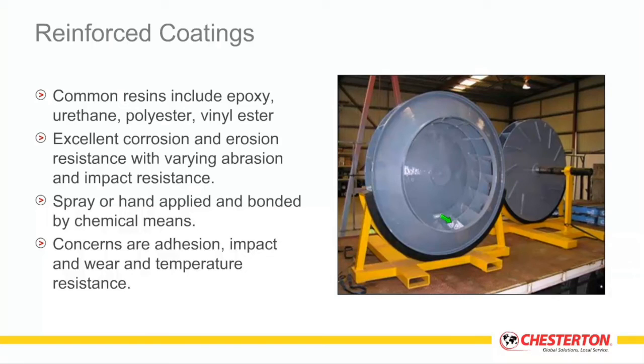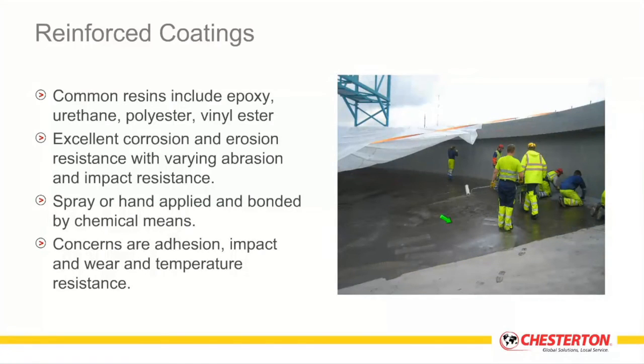The concerns we have with these materials is bonding strength and adhesion, and this is directly related to how surface tolerant they are to preparation and the degree of surface preparation that is able to be achieved. These materials can be applied by spray, they can be applied by trowel, they can be cast as well. And here you see some examples of coating systems.